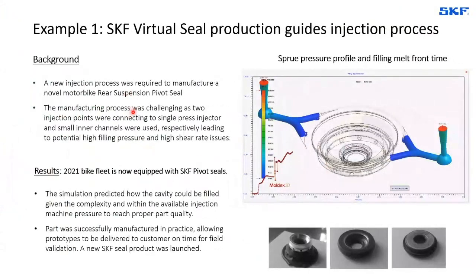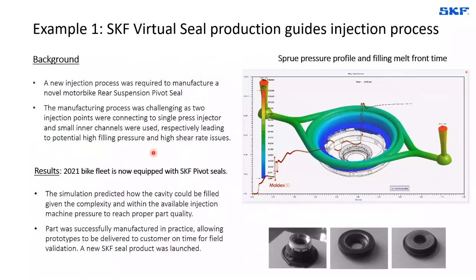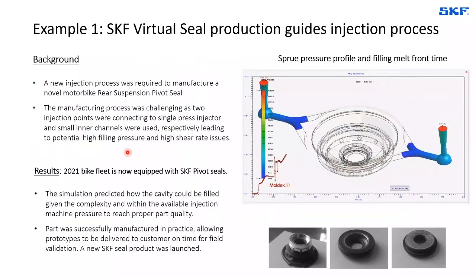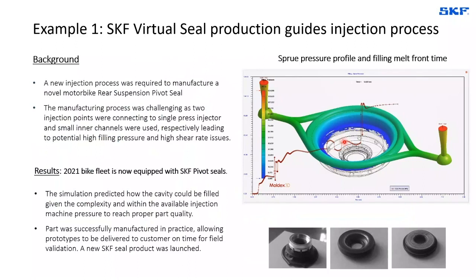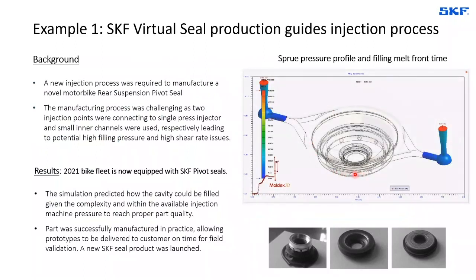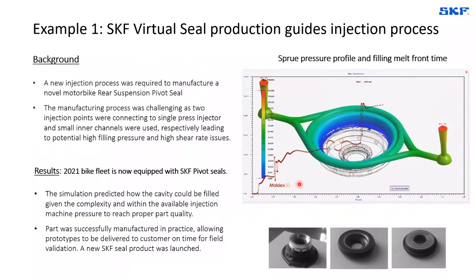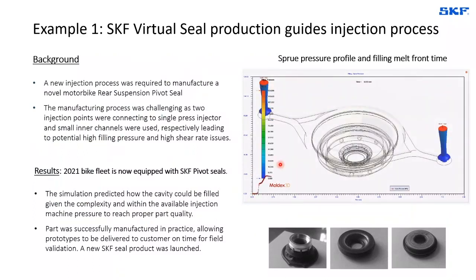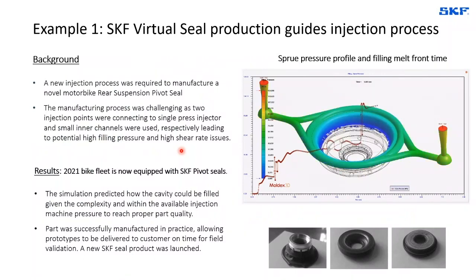One quick example of application I would like to show is a case where we had a request from a motorbike customer that needed a rear suspension pivot seal. And we had a challenge here because we needed to inject the rubber through the metal insert channels in order to mold the two lips in place on the seal. So quite a complexity of the channels internal to the metal insert, because that would lead, in principle, to very high shear rate. And the challenge was also whether or not this could be filled within the available pressure of the press that we had in the prototyping shop.